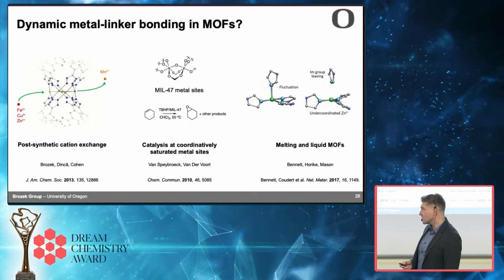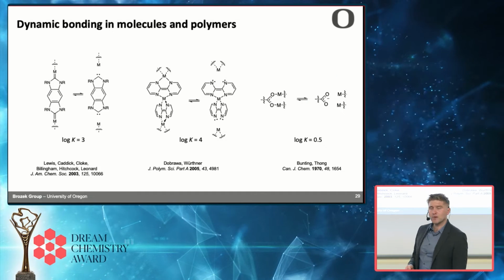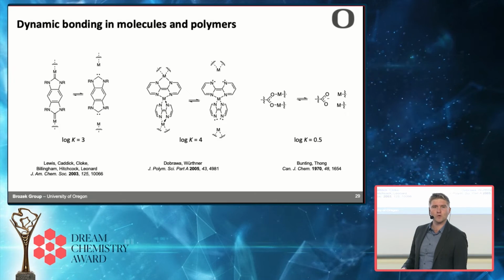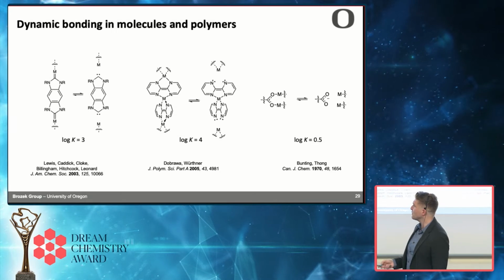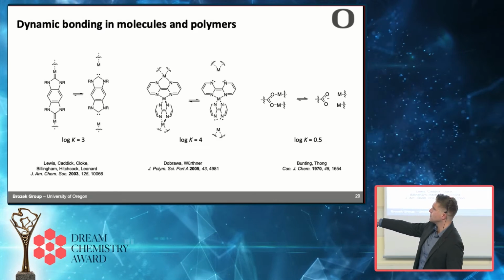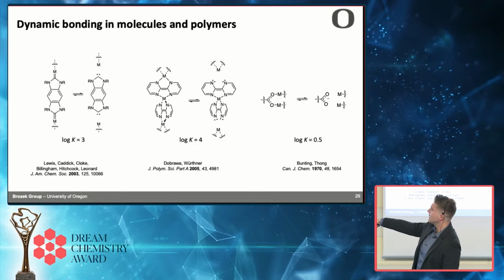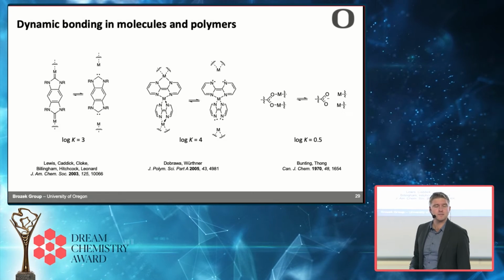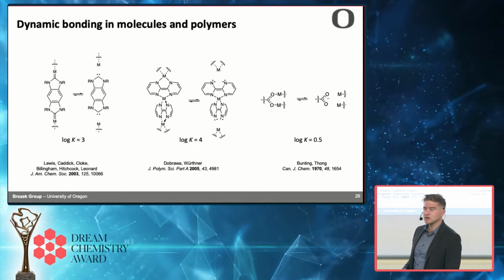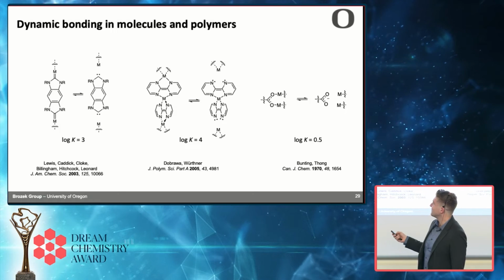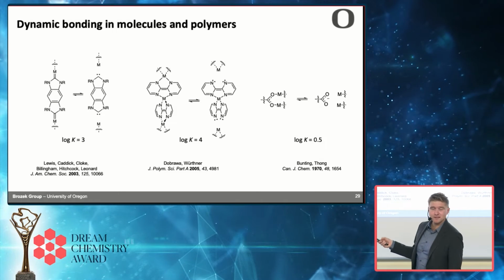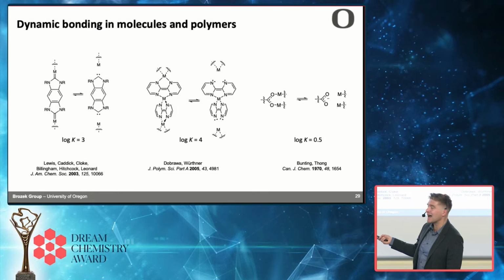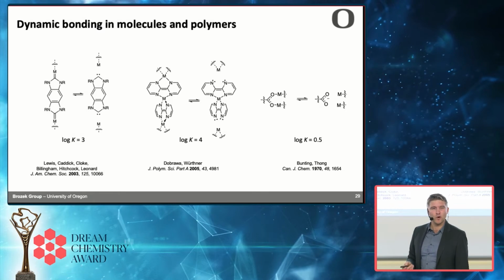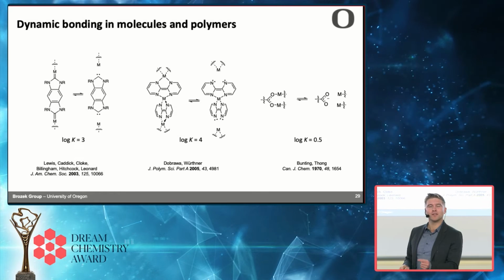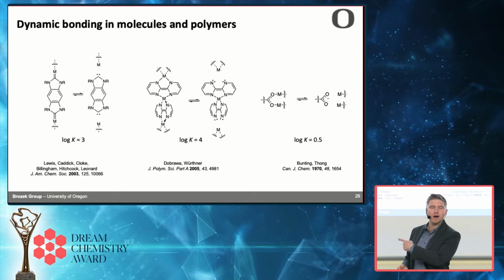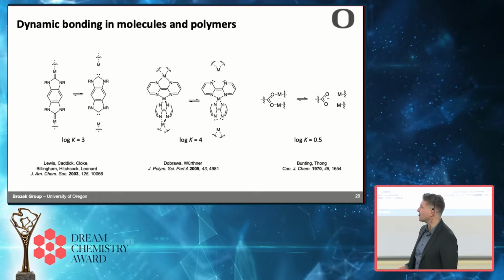So this would still be strange to think about in this field, but if you're a polymer chemist, this is totally conventional. In fact, when people use metal carbene polymers or metal pyridyl polymers, they can measure those equilibrium constants. They're big, but they're measurable. And like I said, people have measured the equilibrium constant for metal carboxylate bonds, and it's tiny. A log K of 0.5 would imply that a third of the time you don't even have bonds. A third of those bonds are broken at any given time.